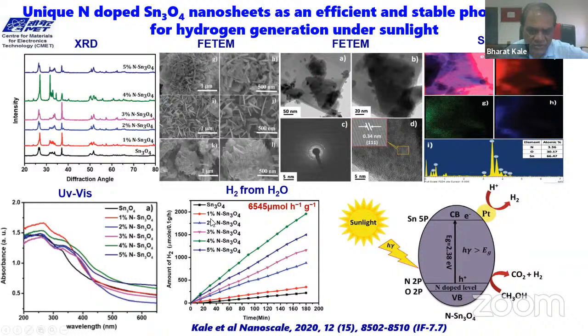You see that 1% nitrogen, almost 4% of nitrogen in the Sn3O4 gives good photocatalytic activity as compared to the others, because as we increase the nitrogen doping further in the Sn3O4, we found a shielding effect observed in the material, so the absorption of light gets reduced because of the high nitrogen content. Most of the nitrogen goes into the lattice, but after some time it also covers the surface, and that kind of situation will reduce the absorption of the light, and we get lower